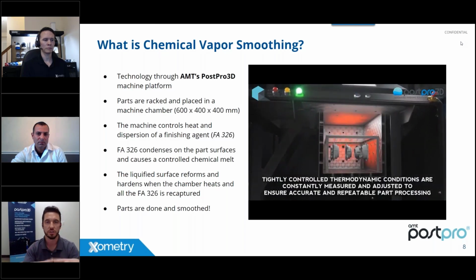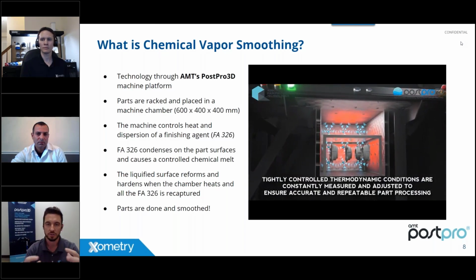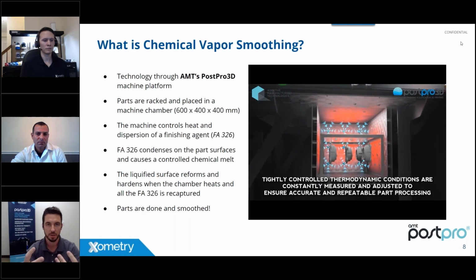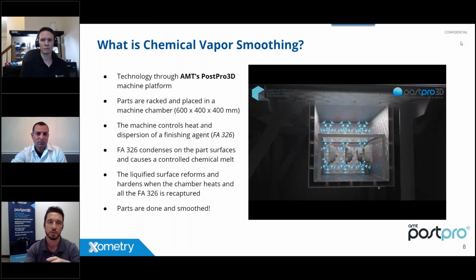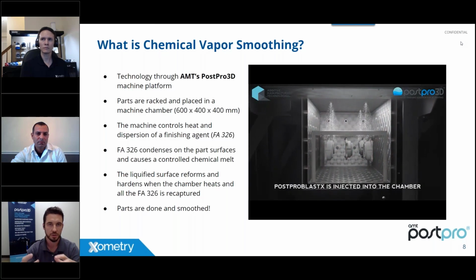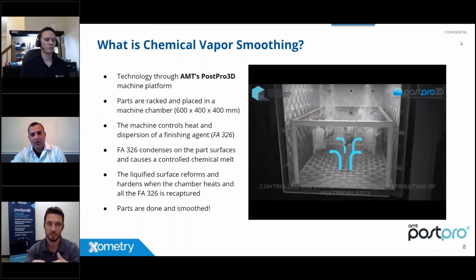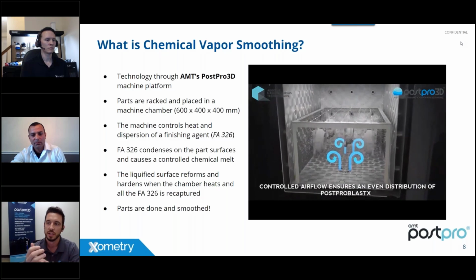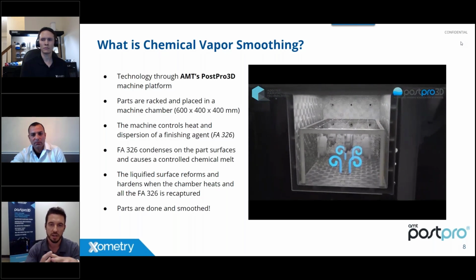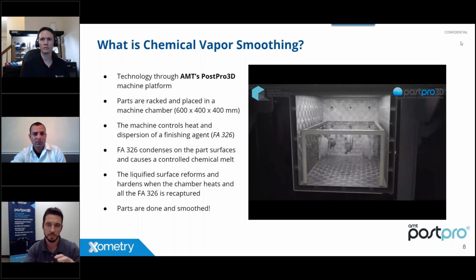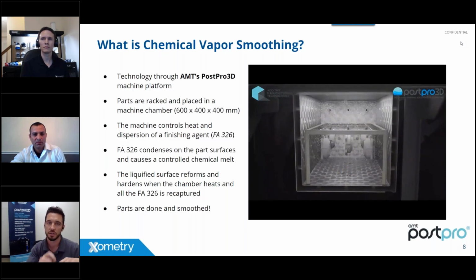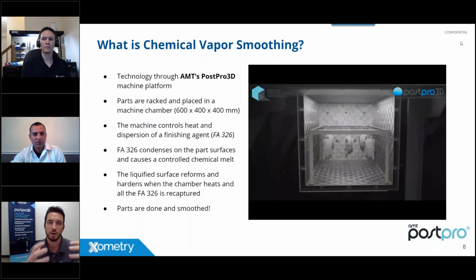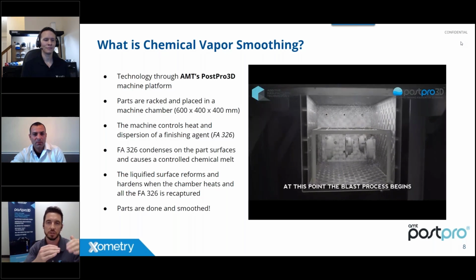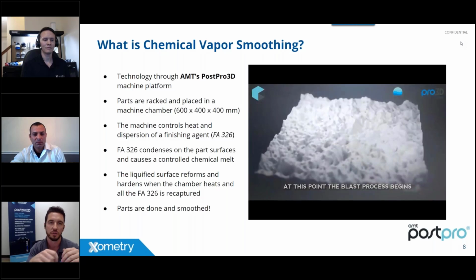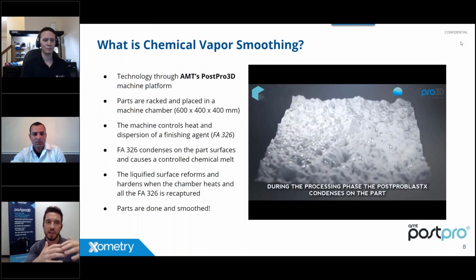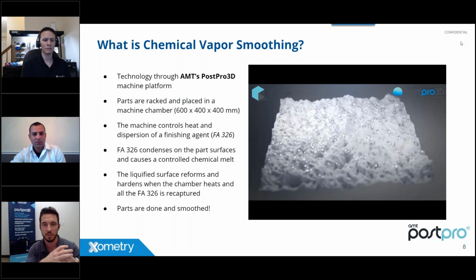And how we do this is we introduce these parts into our closed loop system, and these parts are processed in a very controlled environment. In that controlled environment, we're ensuring condensation on the surface of the part with our carefully selected chemistry. The reason we do that is the condensation is actually putting this as-printed part, or rigid plastic, into a flow state just on the surface. And that flow state is where all the magic starts to happen. We're loosening the sintered part or the fused filament, loosening that up, and it actually starts to flow, like you can see in the image.